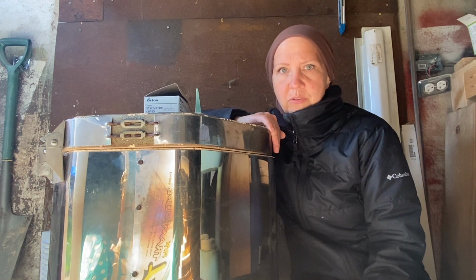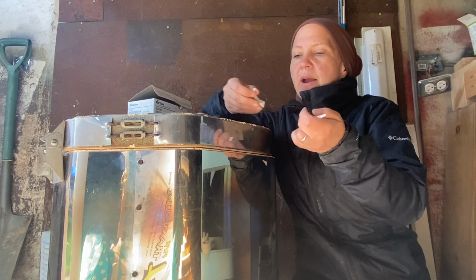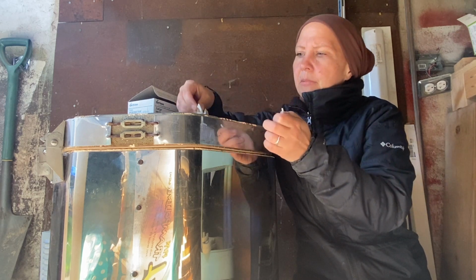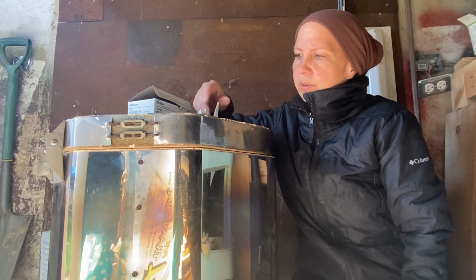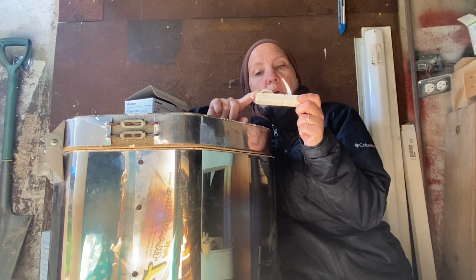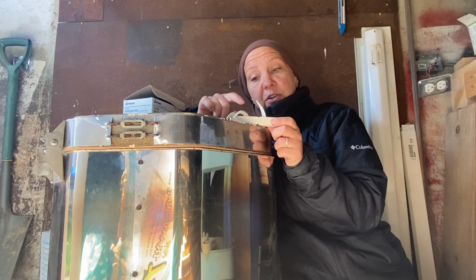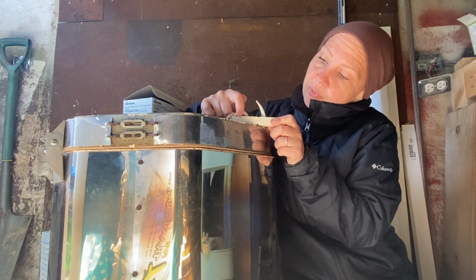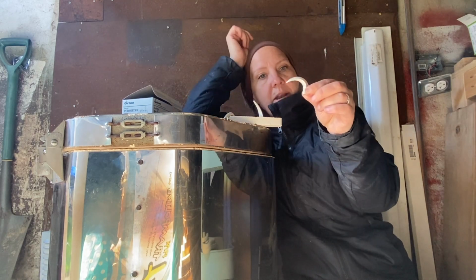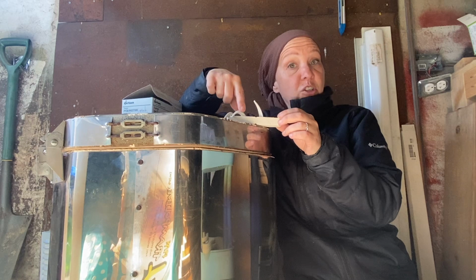I probably have some cones here to give you an example. One sec. The example cones that I have are for a glaze firing, but it's the same principle. This is how you're reading your cones when you're firing. So this is after my fire. My cone that's going to melt first, you can see, is really flopped over and rested on the shelf. The middle one is my target cone, and you can see that it's bent over and pretty much touched the edge of the plaque. And they say you want your target cone to be about 90 degrees when done, so it's going to line up here. And that'll be that I've reached my target cone.